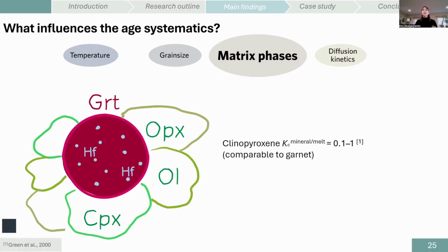As you see, clinopyroxene has a very comparable distribution coefficient for hafnium to garnet, meaning that hafnium would like to exchange between those two phases if it could. But that would lead to the ages of all of the lherzolites being the age of the kimberlite eruption, because that's the only time where they cool down to the closure temperature of the system.